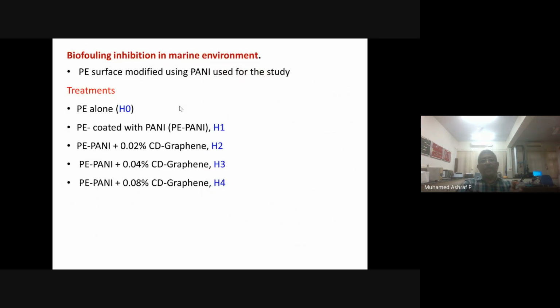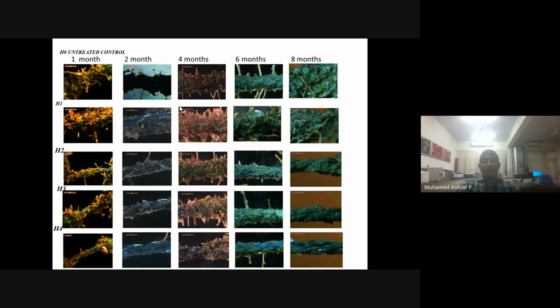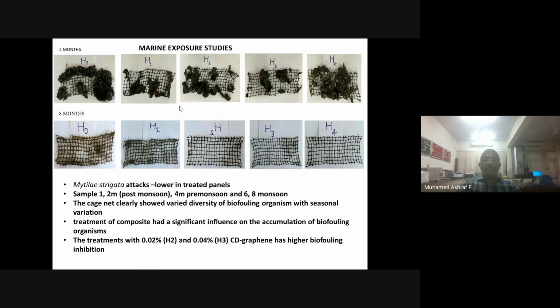And then we studied the antifouling characteristics of this carbon dot graphene system. We gave different types of treatments and exposed these aquaculture cage nets in the marine environment for 8 months. We saw that the treated nets were comparatively good. Then there is one case where we came across Mytilae strigata, which is one of the major issues in the Cochin region because it is an invasive species, and our treated nets were better at controlling it.